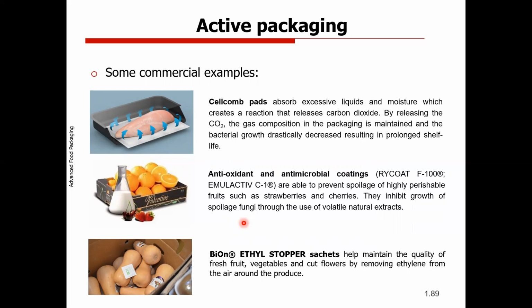These Cellcomb pads. Here we have a system, a pad that absorbs excessive liquids and moisture, and then with this liquid and moisture, the pad has create a reaction that releases carbon dioxide. This is very interesting because it's like a smart packaging that we are developing, because you are only releasing when the liquids are released, and this liquid release is related with shelf life of the product. And by releasing this carbon dioxide, the gas composition in the packaging is maintained and the bacterial growth is decreased, resulting in a prolonged shelf life. So it's very interesting, the approach from this company.